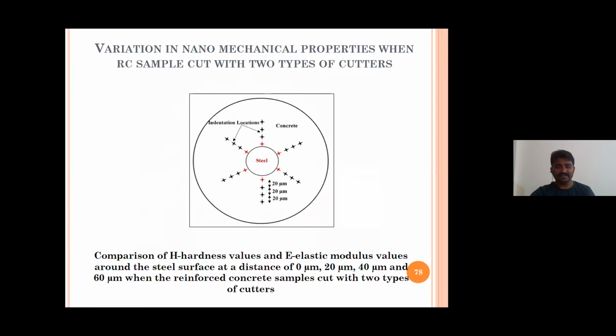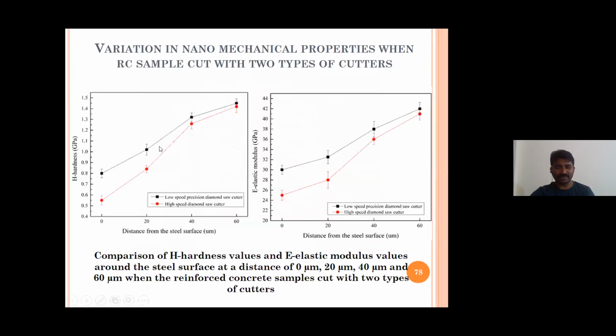Then we have studied the nanomechanical properties also. As you can see, some hardness values against distance from the steel surface. If I use high speed diamond saw cutter, the nature itself is like that. At the interface, the hardness is less. As you move away from the interface, the hardness is increasing. Same goes with the elastic modulus. Why is the hardness and elastic modulus increasing away from the interface?